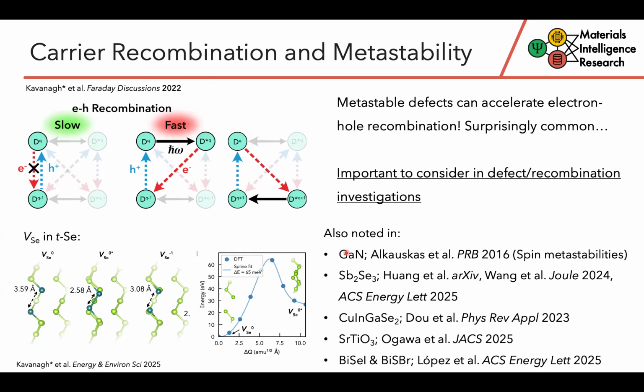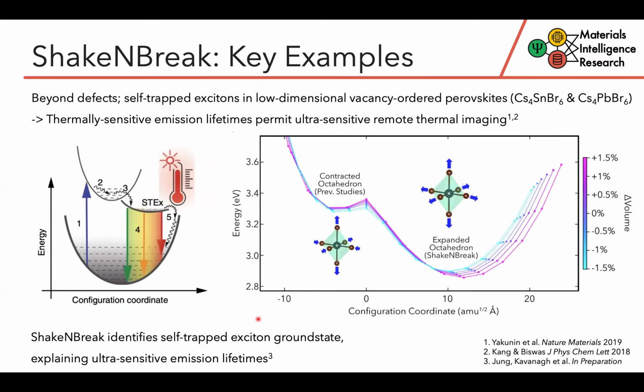catalyze these processes. One other area that we've found ShakeNBreak to be useful is actually beyond defects, looking at other types of localized species, such as polarons or self-trapped excitons, that of course have quite a lot of similar behavior to defects. One example of this was how we used it to explain the unusual, extremely thermally sensitive emission lifetimes of self-trapped excitons in some of these vacancy-ordered perovskite materials, which has been shown to be very useful for some remote thermal imaging applications.